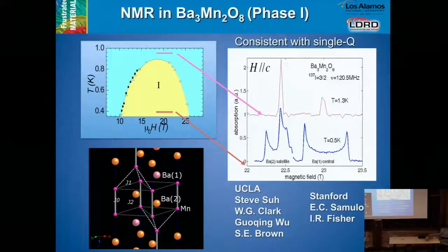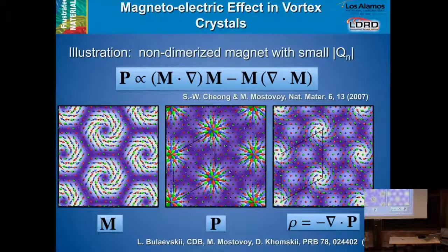Apparently, it's not so trivial to do neutron diffraction with a magnetic field of 9 tesla along the z-axis. To conclude, these magnetic orderings also lead to some microscopic magnetoelectric effects. This ordering also leads to a macroscopic magnetoelectric effect because it has a net ferrotoroidic moment. The ferrotoroidic moment is the sum over all the sites of R cross S, and you can see that is the anti-symmetric component of the magnetoelectric tensor.